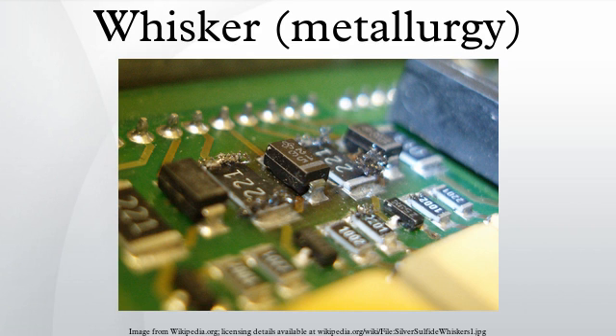At frequencies above 6 GHz or in fast digital circuits, tin whiskers can act like miniature antennas, affecting the circuit impedance and causing reflections. In computer disk drives, they can break off and cause head crashes or bearing failures. Tin whiskers often cause failures in relays, and have been found upon examination of failed relays in nuclear power facilities. Pacemakers have been recalled due to tin whiskers. Research has also identified a particular failure mode for tin whiskers in vacuum, wherein high-power components are short-circuiting. Tin whisker is ionized into a plasma that is capable of conducting hundreds of amperes of current, massively increasing the damaging effect of the short circuit.